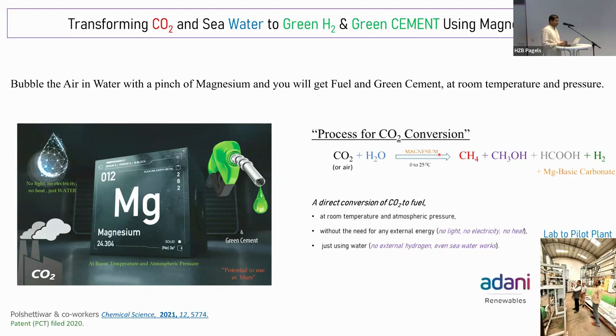But then we realized there are two reactions happening. One is CO2 plus water plus magnesium. Another is magnesium plus water to get you magnesium hydroxide, which is an exothermic reaction. So energy released in that reaction is used by the CO2 reaction. So at the end, you don't need to give any energy. But within the reaction vessel itself, there is an energy transfer.